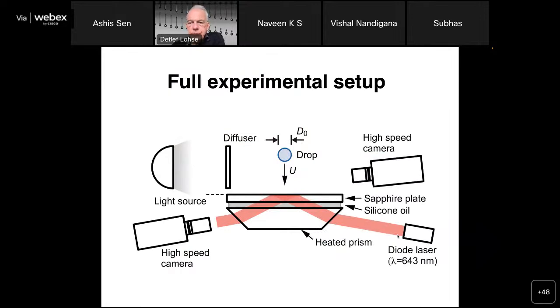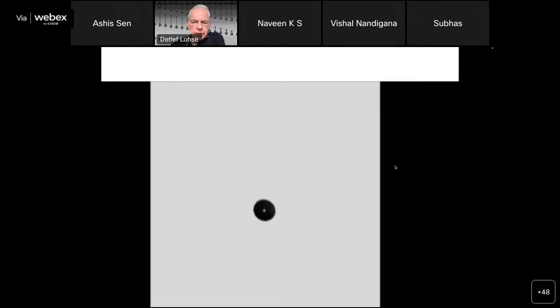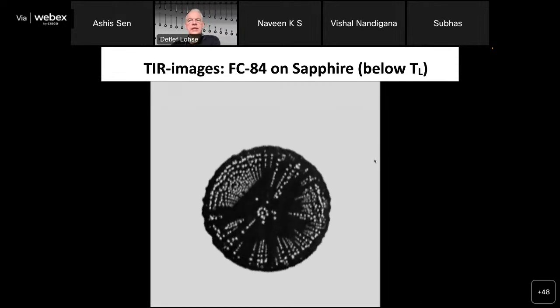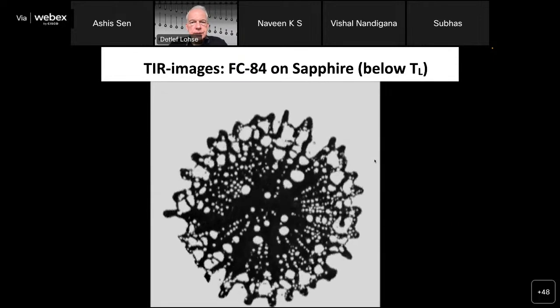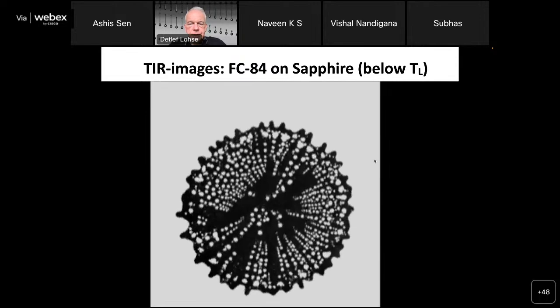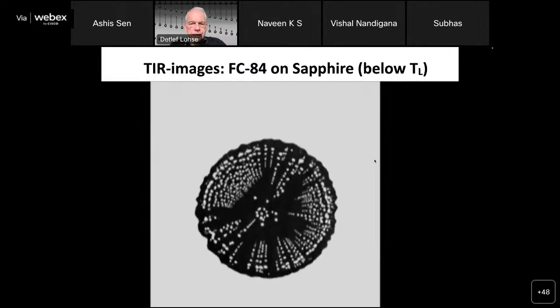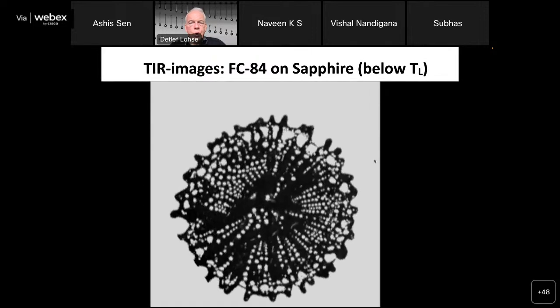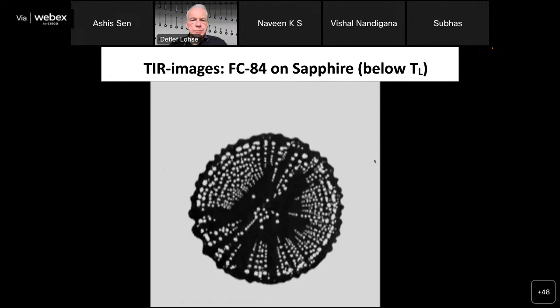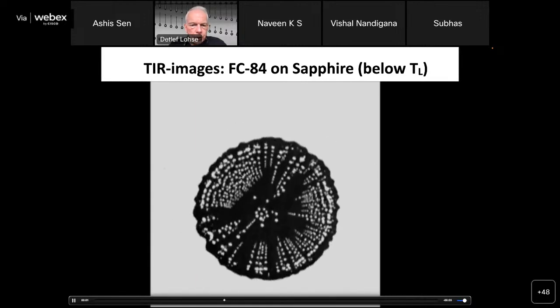So here you see the full experimental setup. We have the droplet falling on the substrate, and we have optical equipment, and we have this prism. And well, we need this heated prism because we want to look into Leidenfrost and then look at what's going on from the bottom view here and also from the side view. And here you see some experiment with TIR. This is FC84, which is a special liquid with low latent heat. And we let it fall on sapphire below the Leidenfrost temperature. And what you see is all these boiling events all over. So it's very, very complicated.